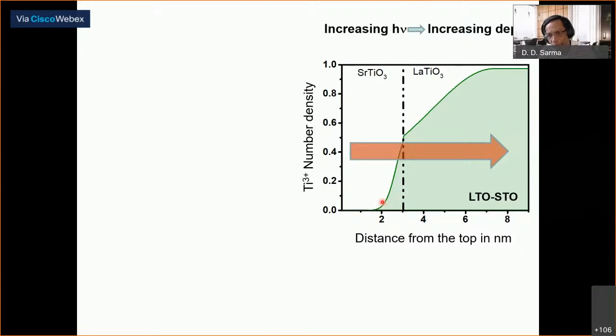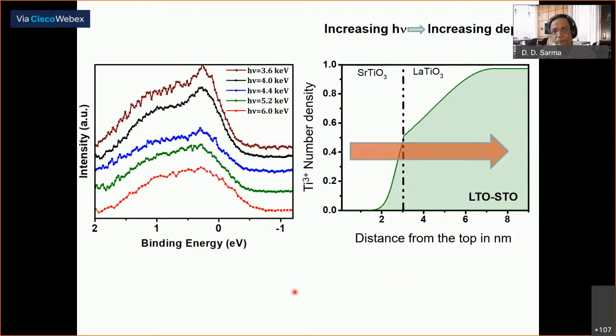This is approximately 1 nanometer deep. There's 3 nanometers here, 2 nanometers. So there's about a nanometer depth of electron doped into the STO site and hole correspondingly doped on the lanthanum titanate site. So the electron distribution behaves in this particular way. Then looking at it, you see that the spectrum is changing in shape as I change. This particular peak, which is high for the 3.6 keV, that means when I'm looking more towards the surface, becomes less, and this one, the Mott-Hubbard sideband, becomes more important as I go deeper with higher photon energy. That is telling me these electrons are less correlated, these electrons are more correlated, because as I look deeper inside, the Mott-Hubbard band becomes more important and coherent intensity becomes less important.